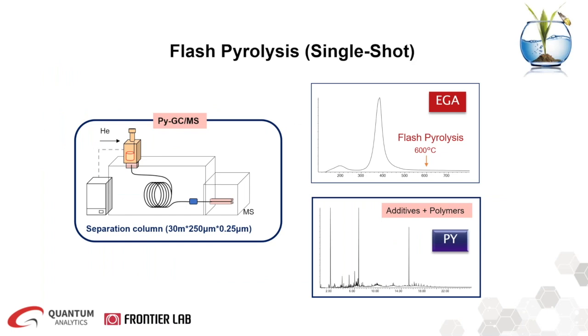This is the flash pyrolysis or single-shot GCMS. As shown here, the EGA was first obtained to identify the optimal pyrolysis temperature, which in this case is 600 C. To perform the flash pyrolysis, the EGA tube is switched to a separation column using the GCMS vent-free adapter. The vent-free adapter allows you to change the columns without venting your MS and waiting for it to be pumped down. So it really saves lots of time and increases efficiency in your lab.